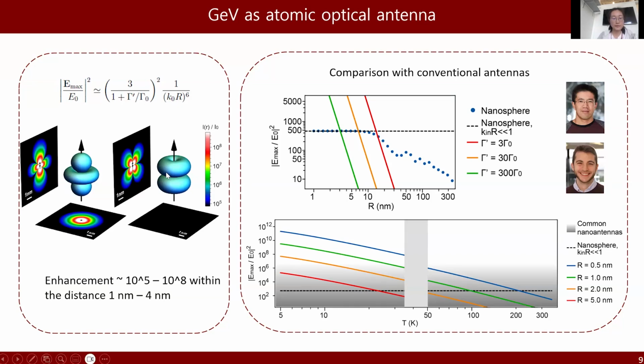From the calculation, we can see that at a distance of 1 nanometer to 4 nanometers away from the GeV, the near field enhancement can reach 5 to 8 orders of magnitude. We also compare the performance of GeV antenna with other plasmonic antennas, such as silver nanosphere, and we found that at small distances, the GeV antenna can outperform the plasmonic antenna. We also noticed that as the temperature increases, the performance of GeV antenna will decay. This makes sense because the increase of temperature will also increase the interaction with phonons.